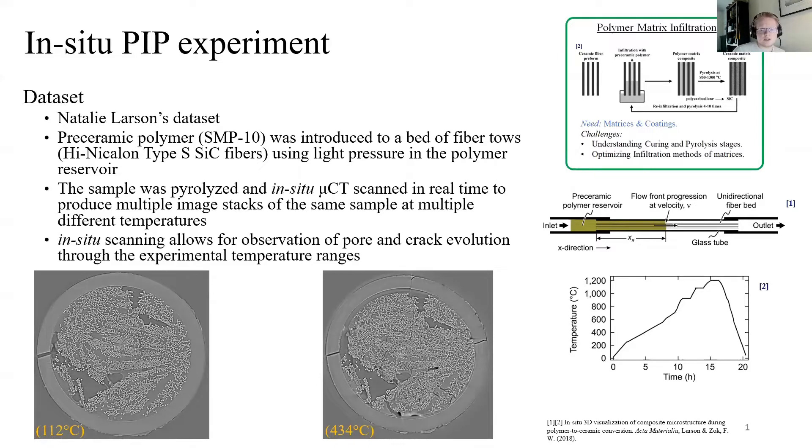In her sample, Larson introduced SMP-10 to a bed of silicon carbide fiber tows and pyrolyzed the sample over the course of 20 hours, periodically taking micro-CT scans of the sample, resulting in 39 2000-image stack datasets that allow for observations of changes within the sample and its microstructure over the duration of the pyrolysis process.